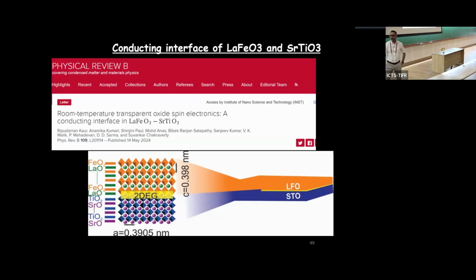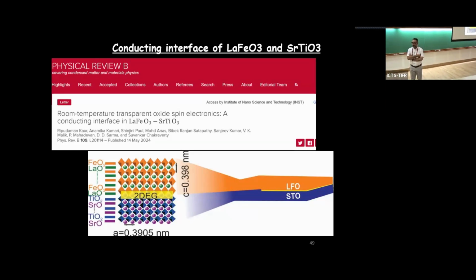So I have a short question. You analyze the Shubnikov-de Haas oscillation data at very high magnetic field because you have a very disordered sample compared to the semiconductor, much lower mobility. So how good is it analyzed? Typically, Shubnikov-de Haas data is analyzed at low magnetic field. This oscillation, how accurate is this analysis? Because once it is non-linear, then you cannot actually index this. Yeah, also your peak was quite broad, right?